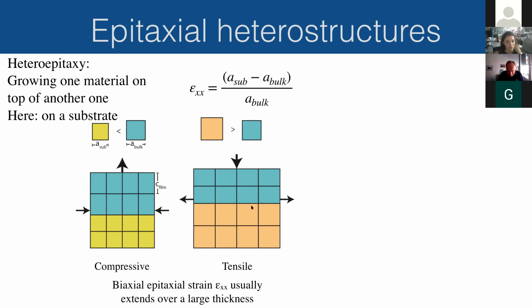And this is called tensile strain. So biaxial strain you can calculate just by comparing the unit cell lattice parameter of the substrate to the bulk lattice parameter of the film you want to grow, and you get epsilon xx, which is the biaxial strain. It's negative if the strain is compressive, and positive if it's tensile. Worth mentioning is that biaxial strain is quite a long-range effect. Depending upon the mismatch between the lattice parameters of the film and the substrate, it's usually over 10 nanometers or more.